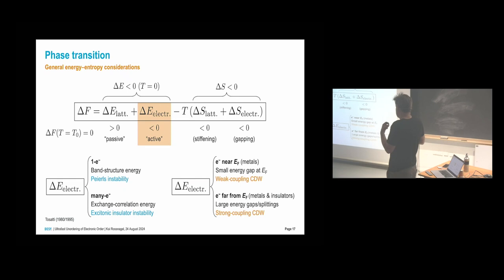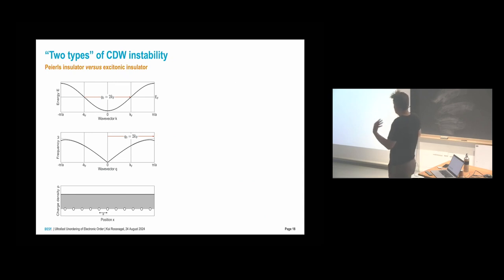And another thing you can ask about this active term is, where does this energy gain come from? Does it come from the energies near the Fermi level? This is when you have a small gap opening, then everything happens near the Fermi level, and then you have a weak coupling charge density wave. But I've shown you in the case of tantalum disulfide, you can always also have a large energy gap, and the energy lowering can also happen at higher binding energies, large gaps, large splittings, and then you have a strong coupling charge density wave. And so you have two types of instability, and you have two types of charge density wave in a way.